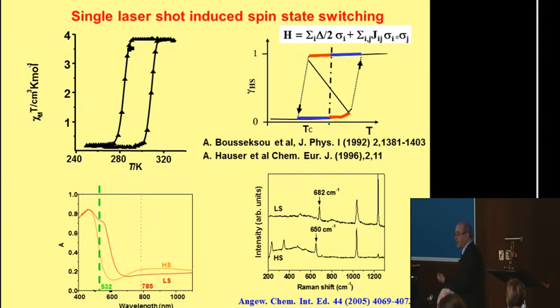The second point is that when you apply your pulse, you can use the laser to write your information. You need to read this information. So you need a way to read the switching. If you look at the Raman spectroscopy from low spin to high spin, you see that when you go from the low spin state to the high spin state, you have a shift of more than 30 wave numbers of this band here. That means that if we use a pulsed laser in the green, we can send our energy. If we also use Raman to read the switch, then we are ready to make the applications.